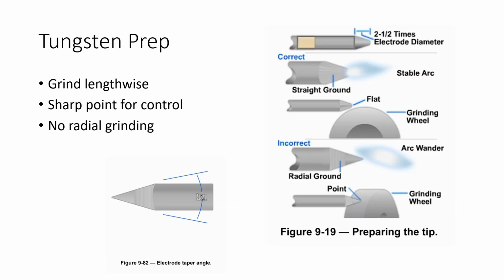So when we're prepping our tungsten for use, here are some ideas on what it should look like. You can see that we want to have it ground lengthwise. We don't want to grind radially. The arc's going to wander if we grind the point radially. We get a much more stable arc if we grind it straight, longitudinally. A sharp point for control, and like I said, no radial grinding on this stuff.